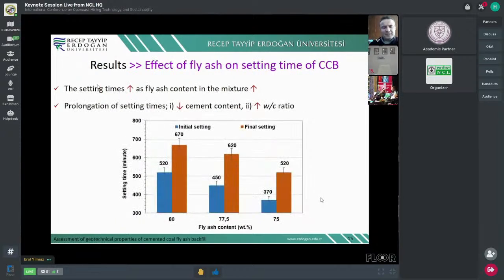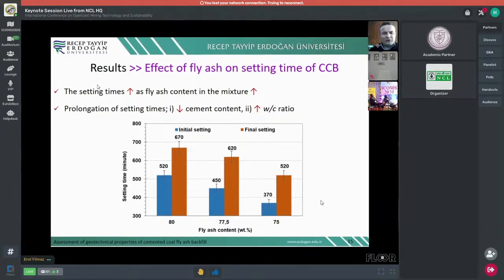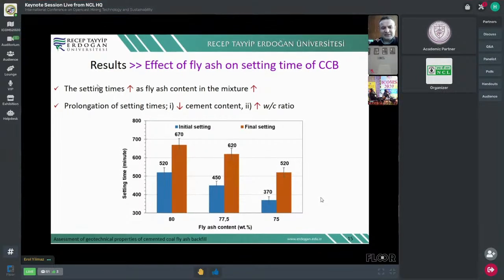Here also the effect of fly ash on setting time of backfill. Again, when you increase the fly ash content in the mixture, you will see the setting times also increase. Prolongation of setting times is affected by two reasons. First one, lower cement content, and second one, higher water to cement ratio.